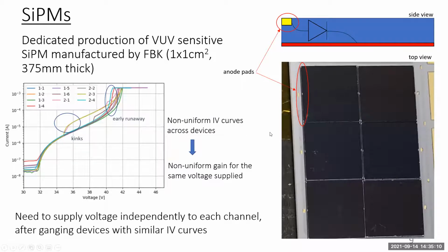Okay, so let me describe very quickly the SiPMs. These are VUV sensitive and are manufactured in a custom run at FBK, 1 centimeter square each. In preliminary analysis, we noticed that some of them have early breakdown or kinks in the IV curves. That, of course, is a problem because if we apply the same voltage across the different channels, we're going to have very non-uniform gain in the light readout. So what we decided to do was to have an independent voltage source for each channel.